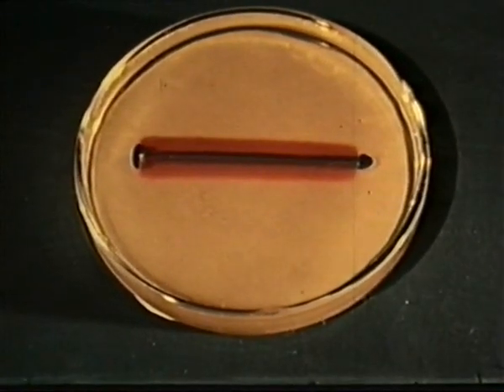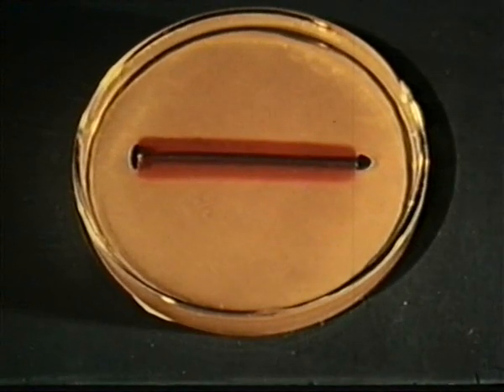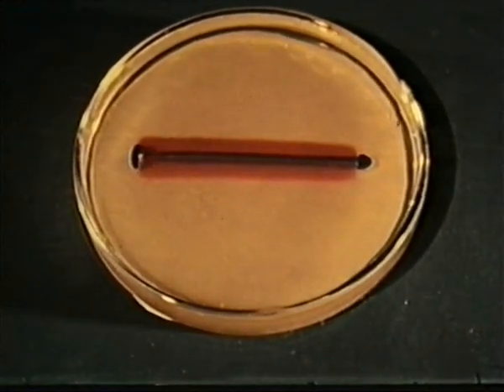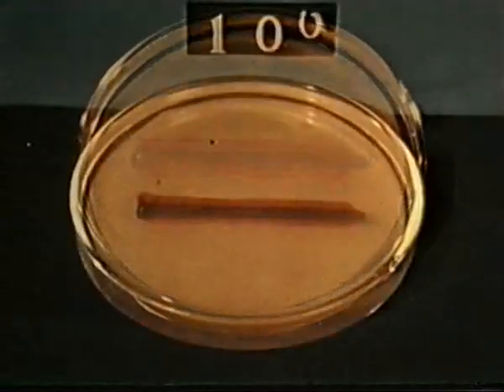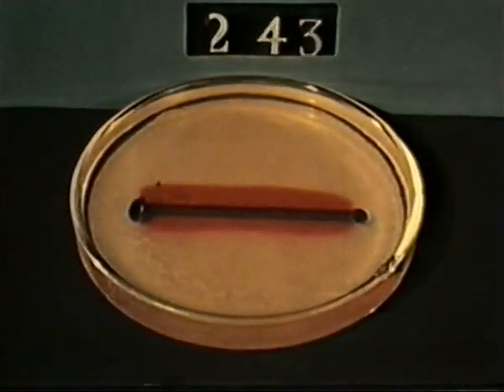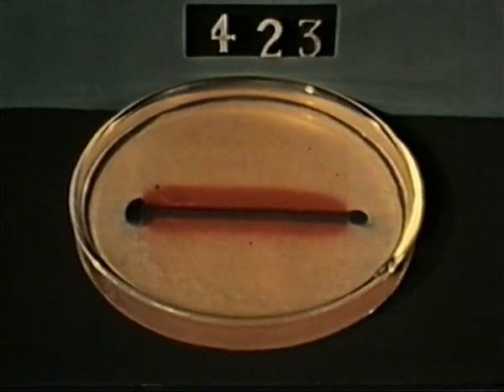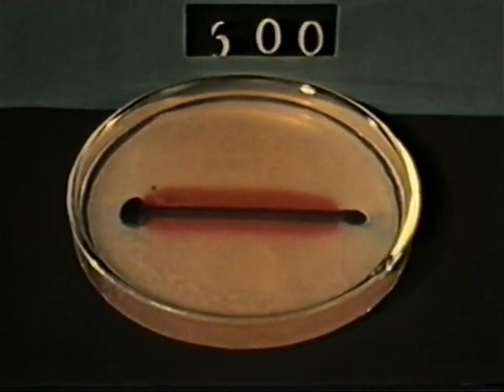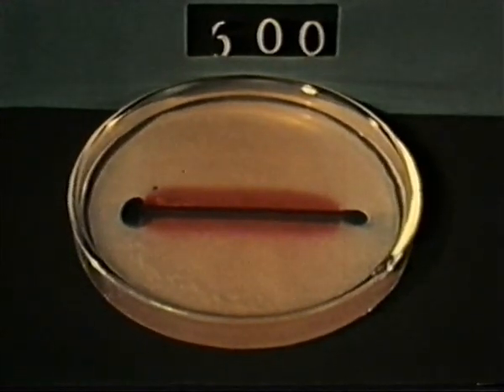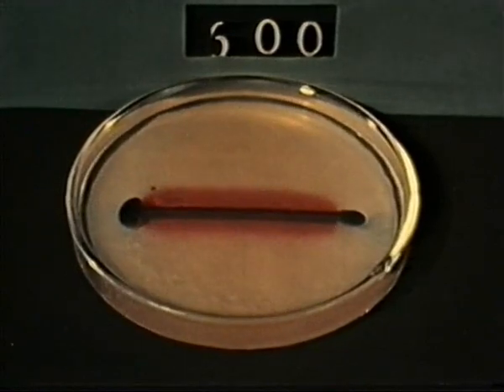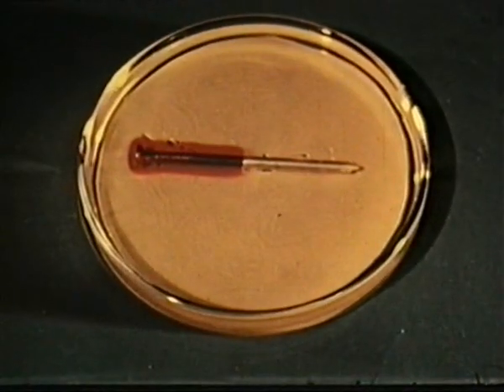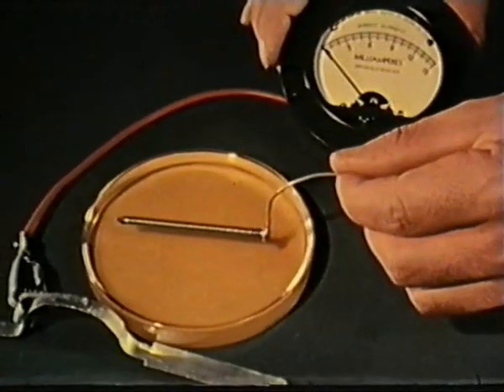So we have shown again that corrosion on a single metal surface is electrochemical and is caused by a flow of current between anodic and cathodic areas. Stop-motion photography again reduces the time required for this action. As we observed previously with the zinc-plated nail, the iron was made to act only as a cathode, and its anodic action was suppressed by the flow of current to it from the zinc. This is a simple example of cathodic protection, which can be illustrated further by similar experiments.